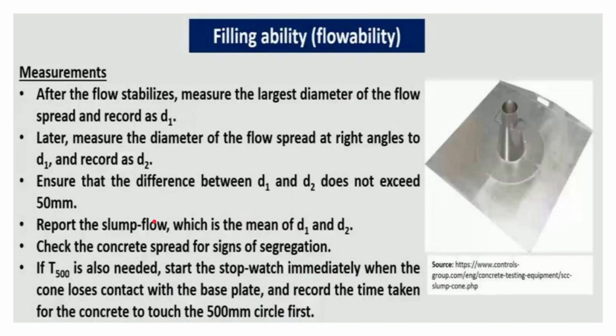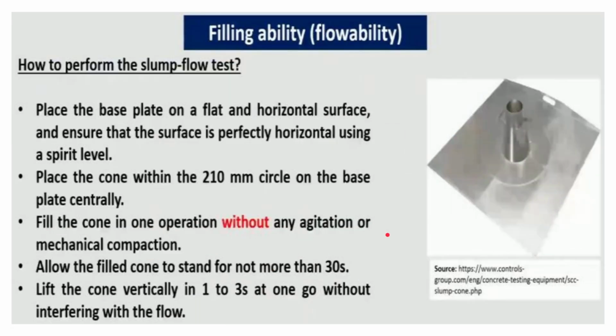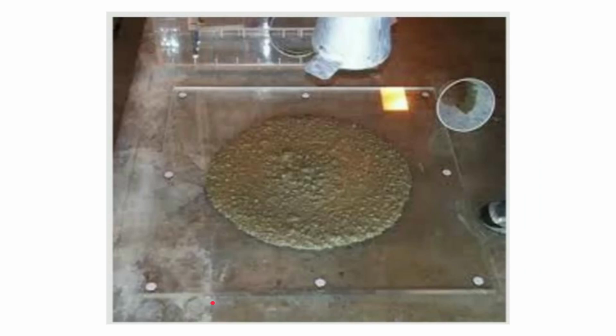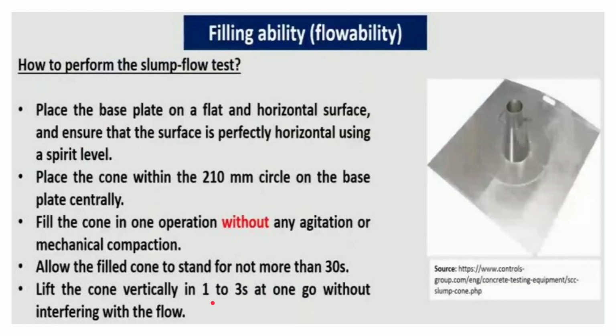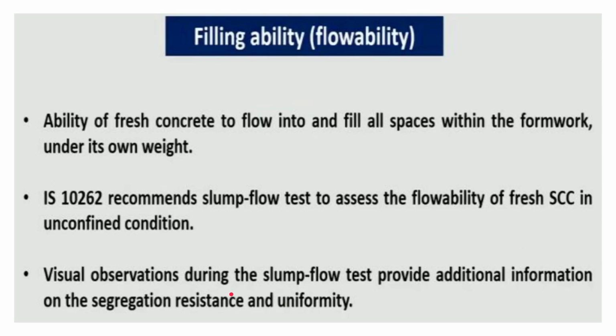Otherwise there will be some other issues, like segregation or other factors may come into play. It will not be homogeneous. Then we report the slump flow, which is the mean of D1 and D2, that is, we take the average. We check the concrete spread for signs of segregation, as we saw in the last slide. So we basically go for visual observation of segregation, resistance, and uniformity.